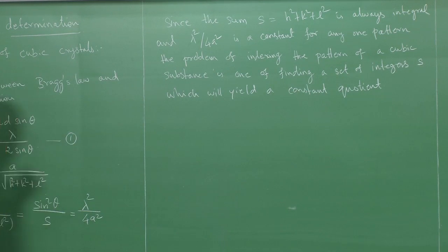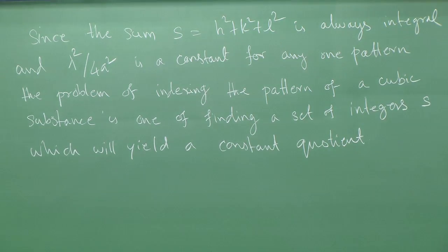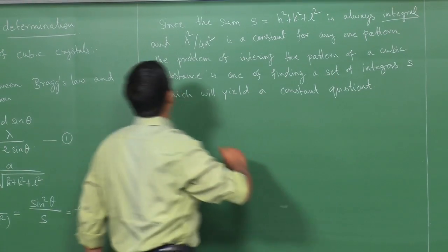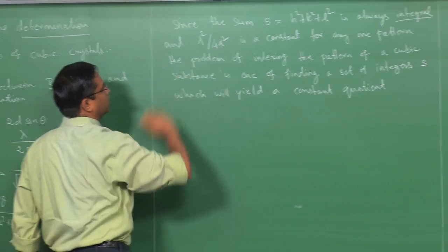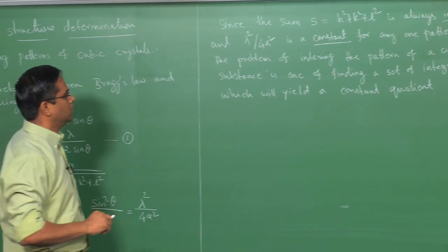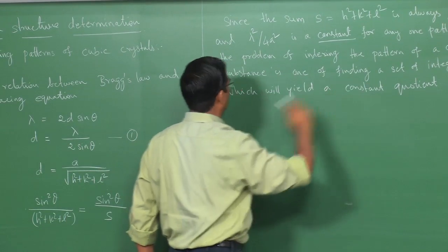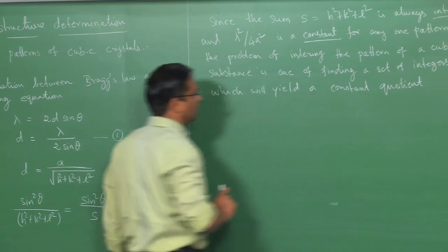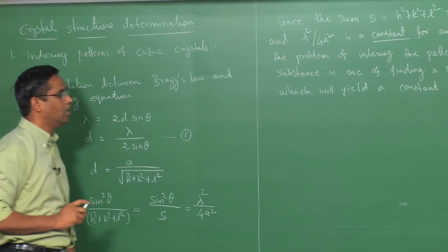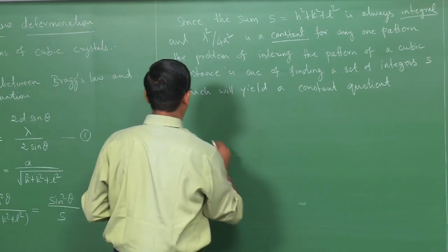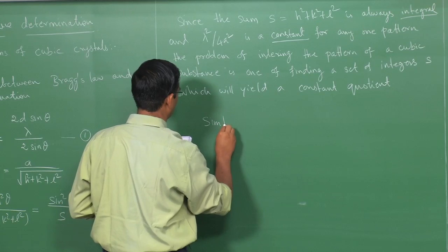So what I have written is the sum h square plus k square plus l square, that is s, is always an integer, and lambda square by 4a squared is a constant for any one pattern. Then the problem of indexing the pattern of a cubic substance is one of finding a set of integers s which will yield a constant quotient. So we can write for a simple cubic,